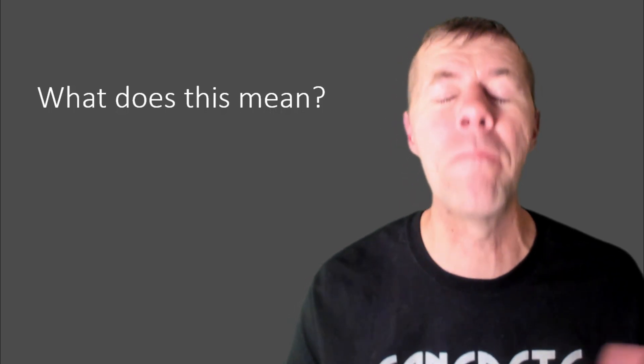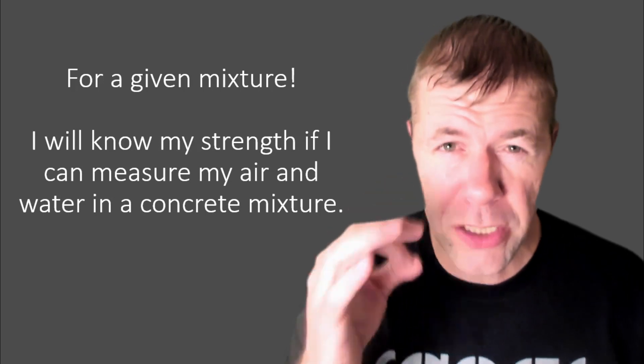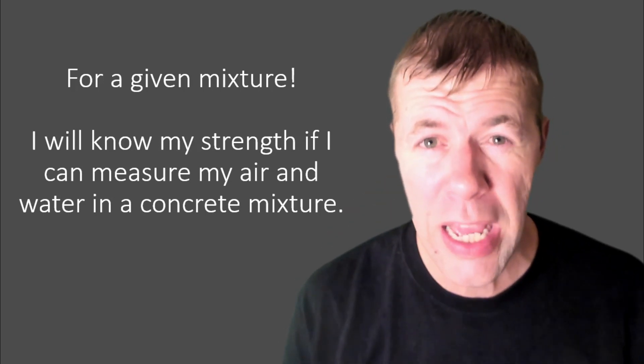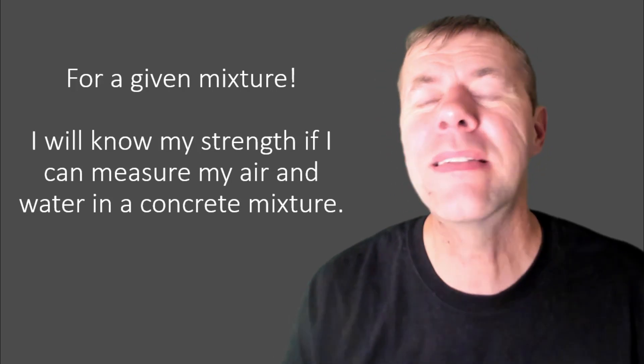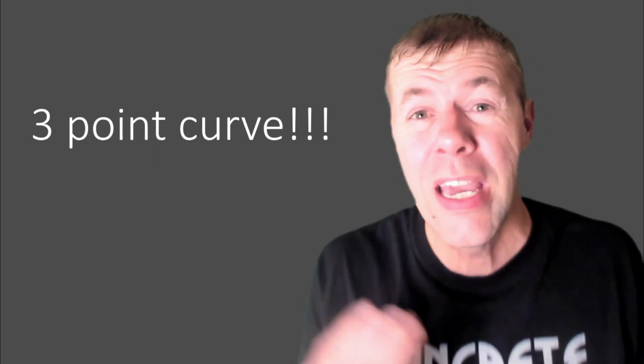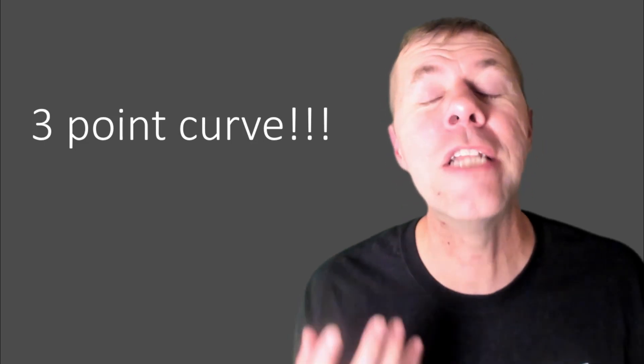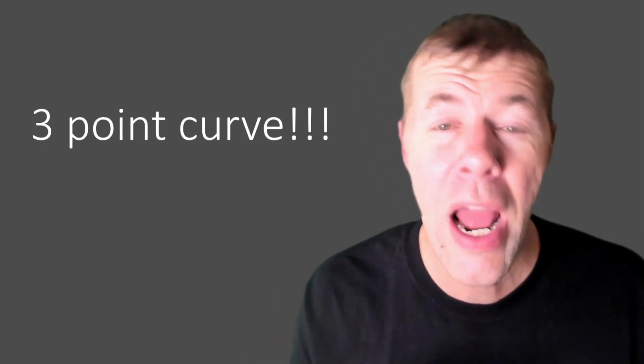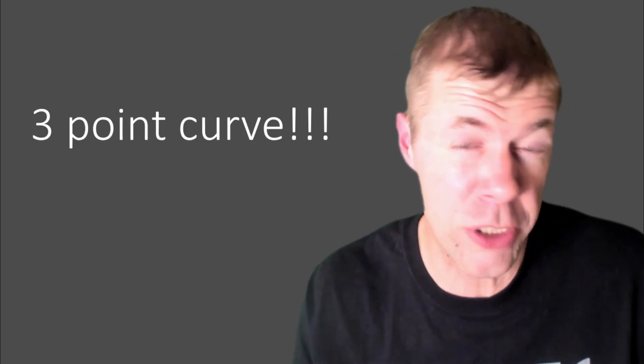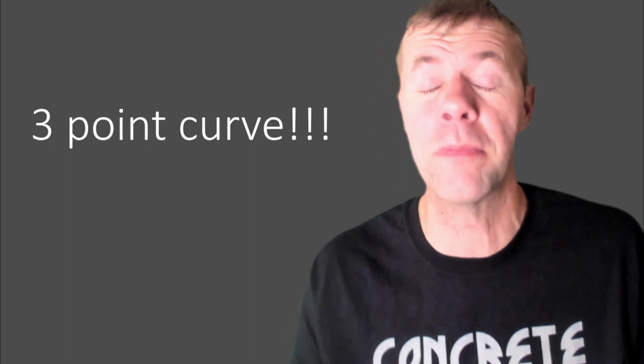But what does this mean? What am I talking about? Well, for a given mixture, I will actually know the strength if I can measure my air and water in a concrete mixture. It's the concept called a three-point curve. If you've never heard of a three-point curve, it's actually really poorly named. It uses way more than three points, typically. It's pretty much how air and water-cement ratio impact strength. So I would call it the air-water-cement ratio curve, or something like that, or the strength master curve, possibly.